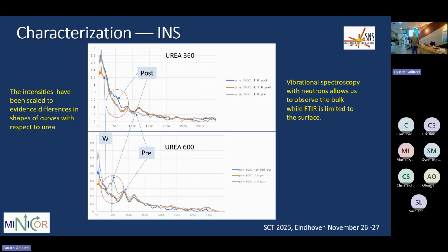Okay, so we have inelastic neutron scattering, and there it can be compared with Fourier transform infrared spectroscopy, but it has a different behavior than FTIR because it doesn't depend on electromagnetic selection rules or transition laws. So it basically follows the movement of the protons inside the material and how they move and vibrate. So actually you can see modes of vibration which you can't see with electromagnetic radiation. So in some cases you can see movements that are not seen with X-rays or laser systems. Okay.